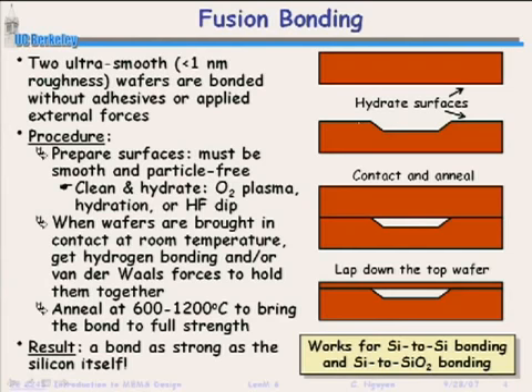Just like the capillary forces that cause stiction that we studied, if you take these two wafers and put them together, they're going to stick together. So you get hydrogen bonding that keeps them together. Then you stick them in a furnace and you anneal them at a high temperature, 600 to 1200 degrees C. This basically melds the silicon together, until you get a really strong bond between silicon and silicon. You can also do this silicon to silicon dioxide. But this is fusion bonding. This is where you actually take the whole thing to a very high temperature to get these bonded very well together. So this is one style of bonding that people have used quite a bit. Here's an example of exactly the process that we were looking at there, something similar to that.